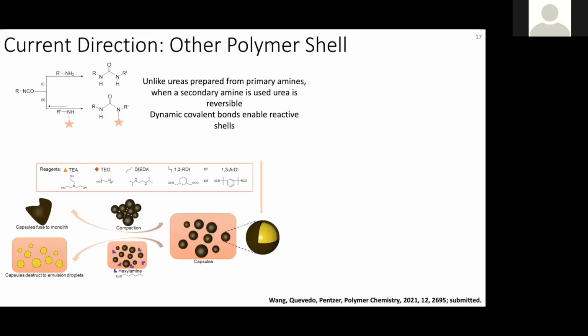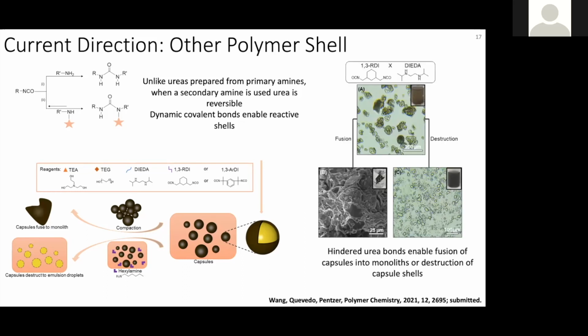So the idea was by incorporating some of these hindered urea bonds into the capsule shell, we could then either compact the capsules and heat them up above the temperature needed for the bond reversion, and we could then have cross-linking between capsule shells. Alternatively, if we take the capsules in the presence of a primary amine, so hexylamine in this case, and we heat them up upon the reverse reaction, the isocyanate that's formed ends up getting siphoned off by the primary amine, the hexylamine, and we then destroy the capsule shell. And so Yifei showed that she could indeed access both of these reaction pathways.